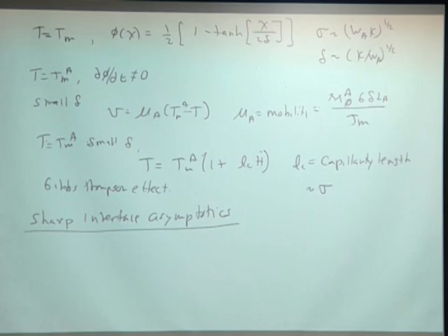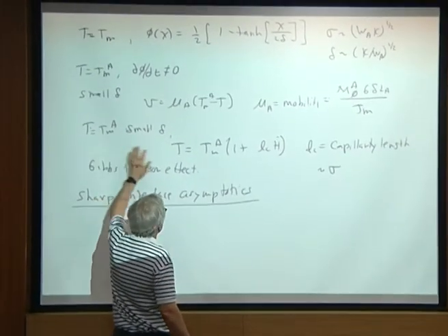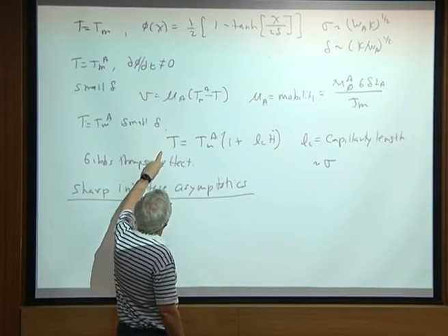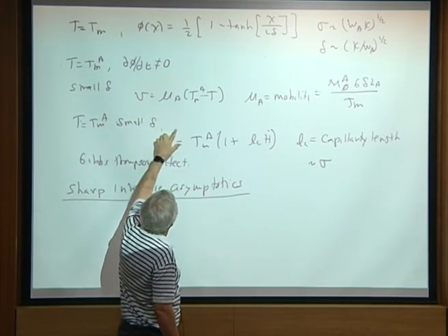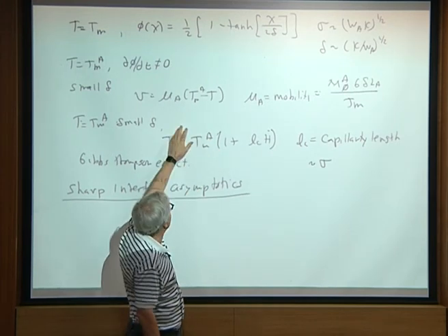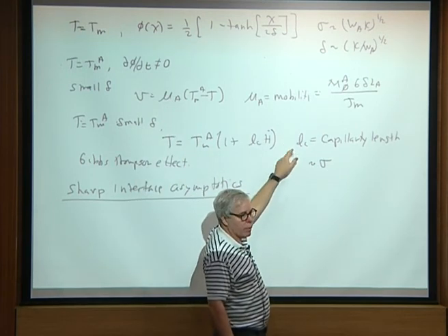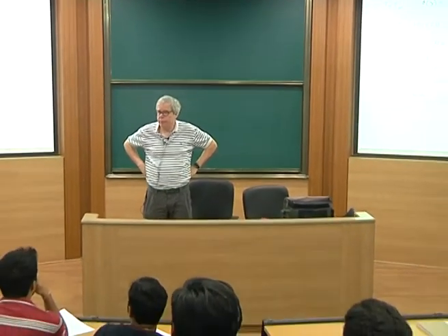There is also a kinetic term with the velocity. Yeah. So what people will do, so this is at the equilibrium melting point. And if you have a non-zero interfacial velocity, what you'll do is you'll divide by mu, and that becomes a delta T, and you'll just add it to this equation. So you'll have a departure from the equilibrium melting point given by this. And so you'll get T is equal to Tm plus V divided by mu. So that you just add to that equation. Other questions? Other comments?